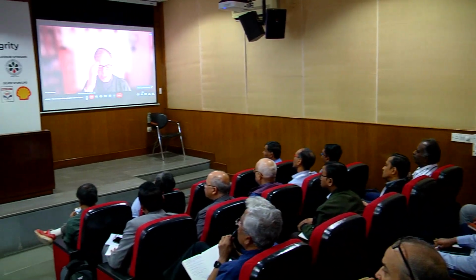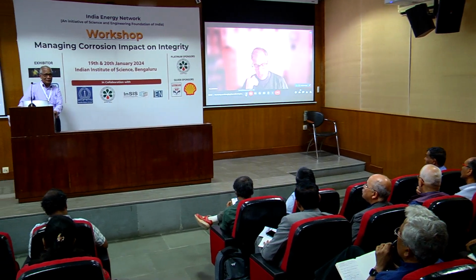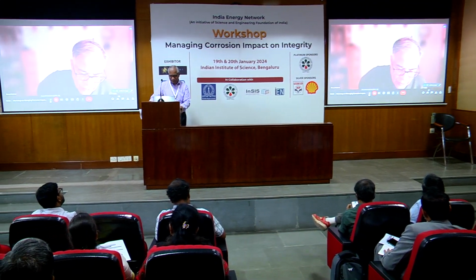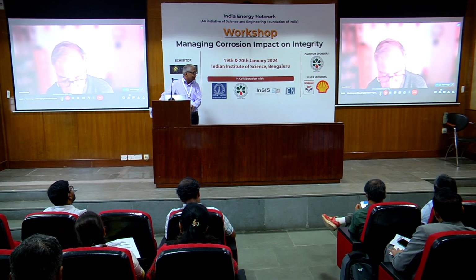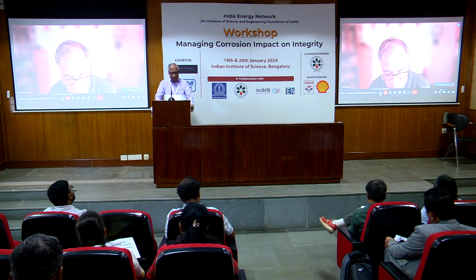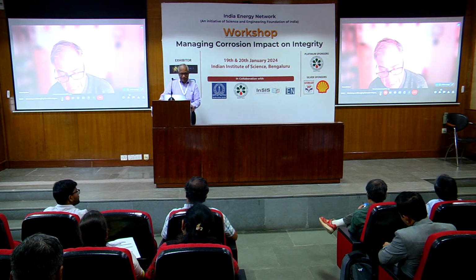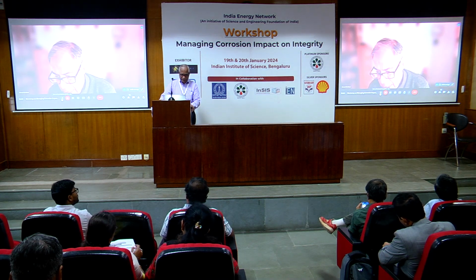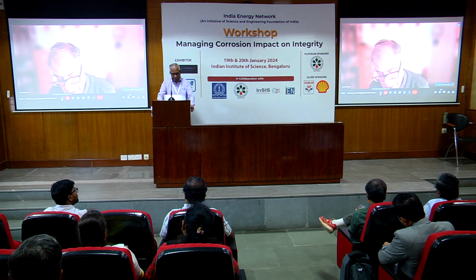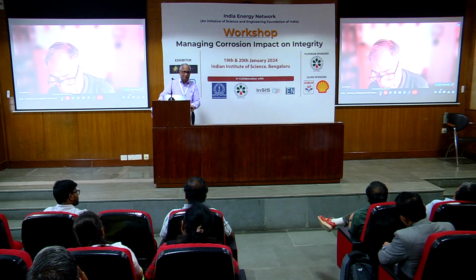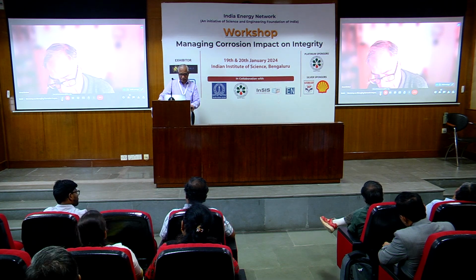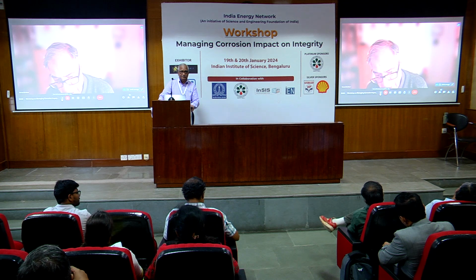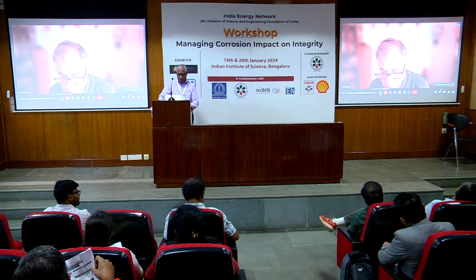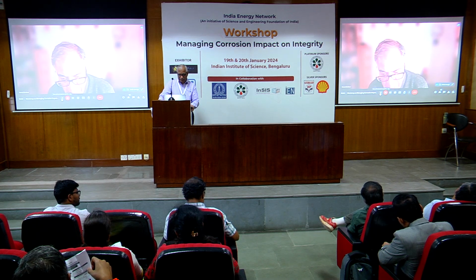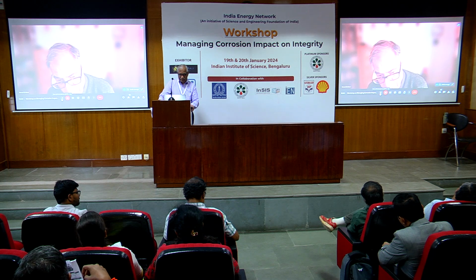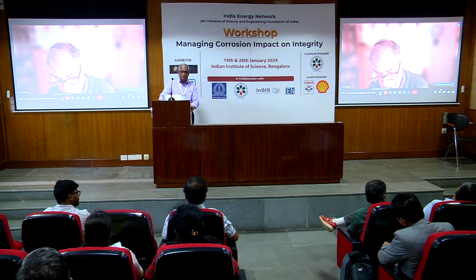Well, this is a subject of ongoing work. I'm involved in a major project in California because the state of California wants to make our economy more hydrogen-based, and that involves repurposing our gas pipelines with hydrogen. The main concern, of course, is the hydrogen embrittlement of steel. And the concern is the reduction in fracture toughness, as well as the increase in crack growth rate with hydrogen. One concern is that even a small amount of hydrogen seems to significantly reduce the fracture toughness of pipeline grade steel.